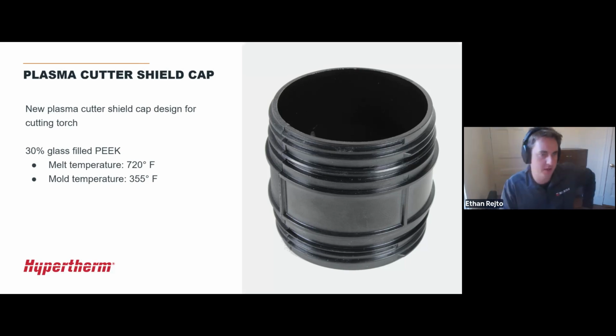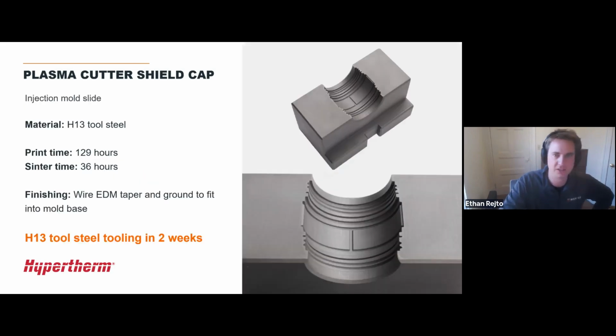This was being molded in a 30% glass-filled PEEK. The melt temperature on that was 720 degrees Fahrenheit, and they were actually heating the tool to 355 degrees Fahrenheit to improve the moldability of this PEEK material. So very abrasive, very high temperature material. This is actually a slide component that's used to form the outside of that cap. They printed it in H13 tool steel, about a 129-hour print, so a little less than a week of printing. Of course, that's fully unattended, so all that time is just the printer working on its own.